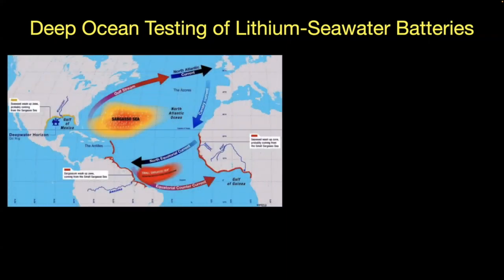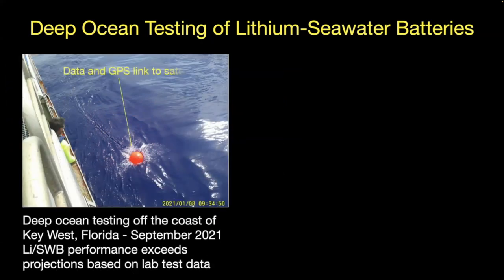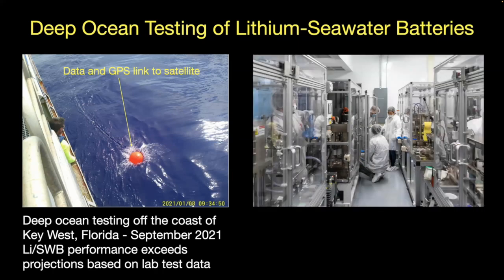We did some tests off the coast of Key West in the Sargasso Sea, a couple of miles below the surface of the ocean. So this deep ocean testing, the battery itself outperformed our internal tests at Polyplus. You can see there's a float, which is tethered to the battery with a data and GPS link to a satellite so we could get that information back. So these batteries are performing exceptionally well.